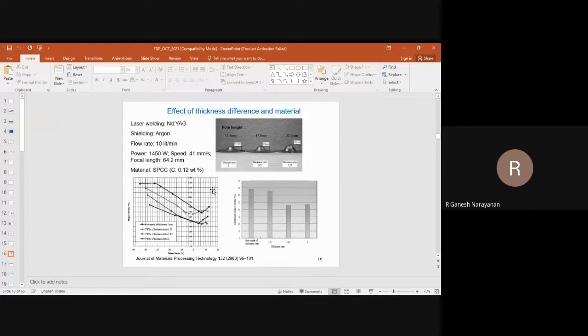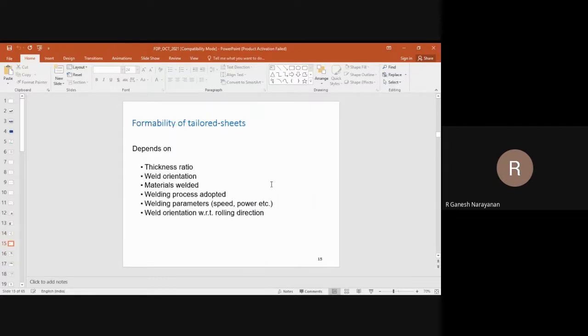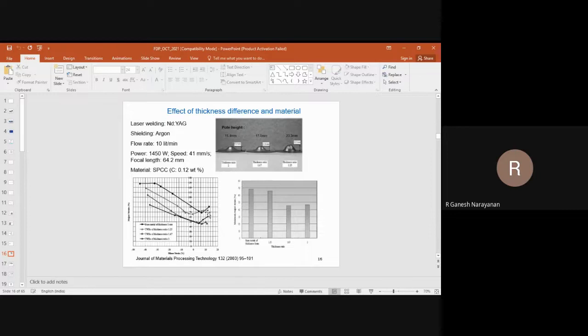You will see that they have constructed a forming limit diagram, the same forming limit diagram which I showed you a couple of slides before, schematic. The same thing has been evaluated here. The black one, the topmost, is the base metal. Below the base metal curve you have a large window, which means a larger region for safe deformation. That means the base metal has better formability. When you speak about tailor welded blanks, they have different combinations of thickness ratio: 1.25, 1.67, 2. With increase in thickness ratio, the forming limit comes down; this curve moves down. The square symbol is for the base sheet, and this diamond is for the 2 mm thickness ratio.